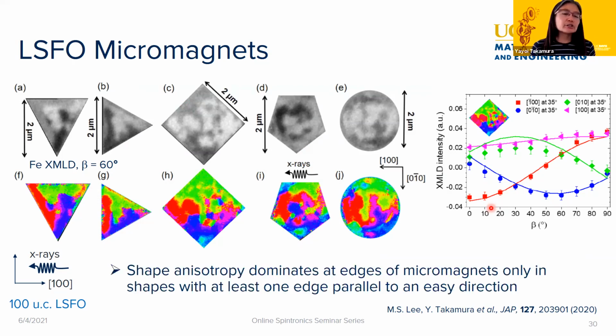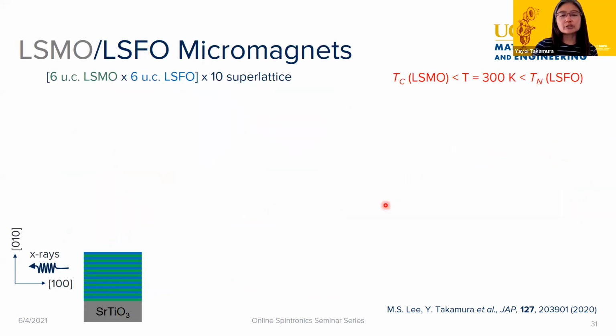And so we got some interesting effects. If we had the pentagons and the circles, basically almost none of the edges are along the easy axis. We get all the really small domains, and they're random and don't have a preference for any of the edges. But then if we went to these triangle regions where we have very few sides, and at least one of the sides was along one of our easy axes, then we actually see the filling of the shape through most of it, which is a very few number of domains. So we basically only get 3 domains in the triangles, whereas we get many, many domains once we start having more edges. So again, showing that we can control antiferromagnetic spins through the shape.